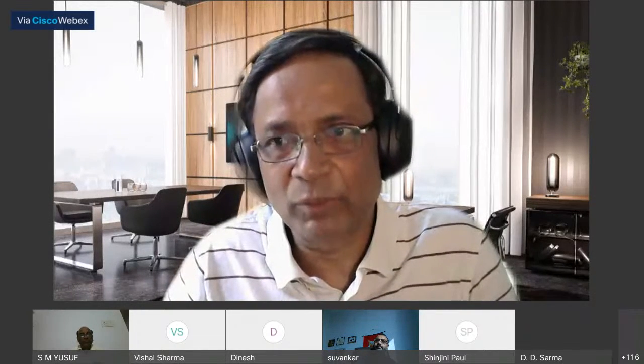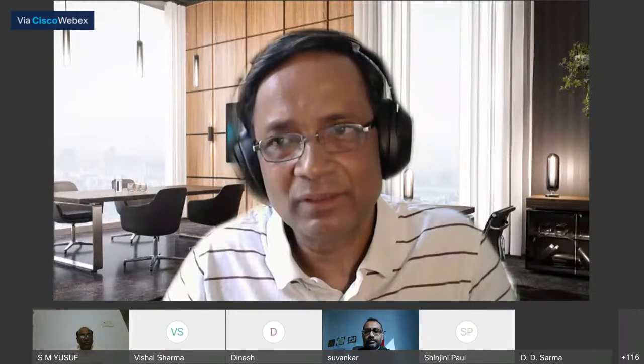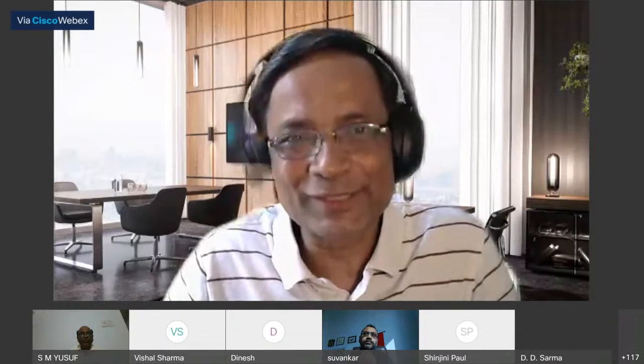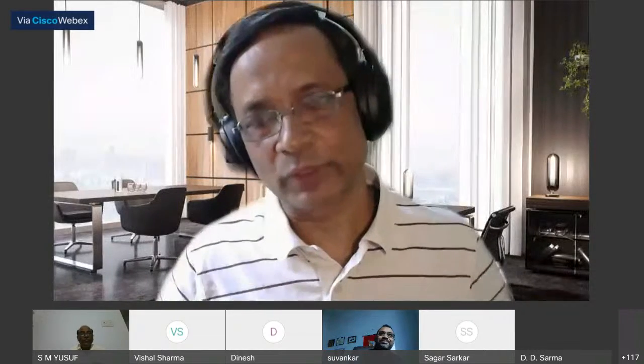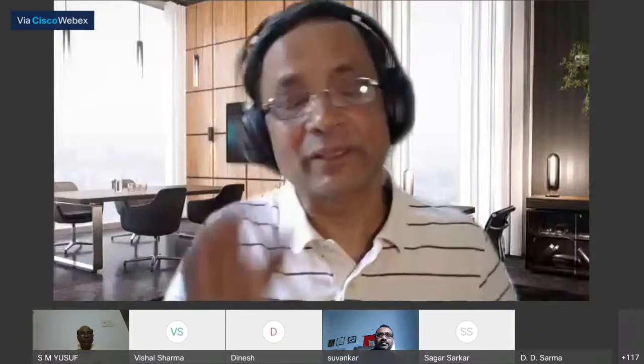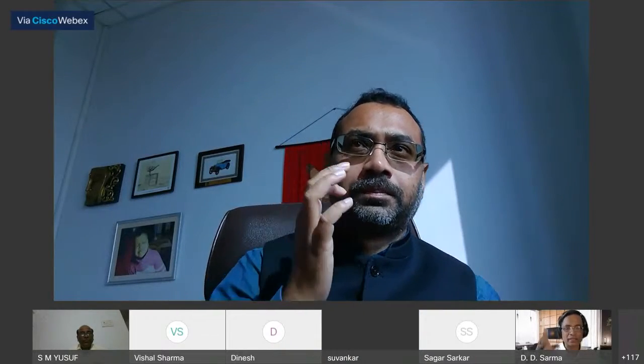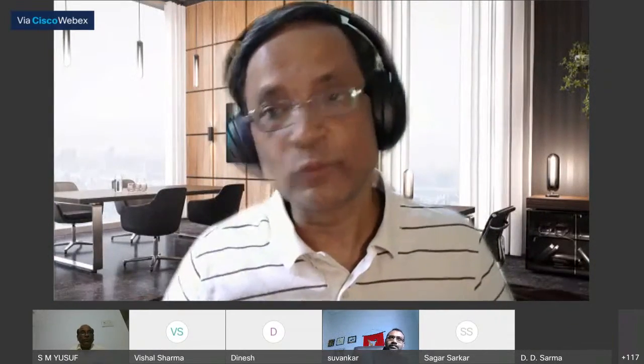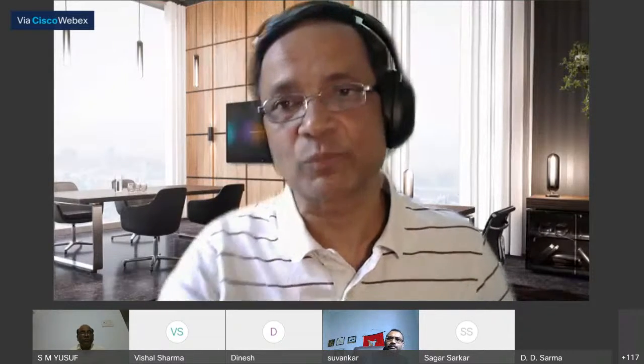Okay, yes, sir. So that doesn't really bother. What was the first part of the question, sir? The first part is the range of photon energy you choose for your experiment. That they start from this photon energy and go up to this photon energy, depends on what factors? It depends on the synchrotron radiation center where we are, or rather the other way around, that we look for the synchrotron radiation center that can give us the photon energy that is required to look at the kind of thickness that you are looking at. Remember, the photon energy decides how deep I can see. All my studies ended, all my graphs ended at about 30 nanometers, and we don't see beyond that because we are limited to about 6.5 kilo electron volts photon energy.